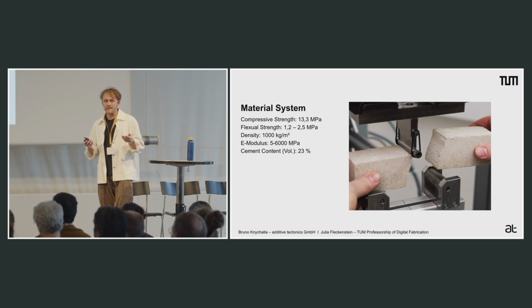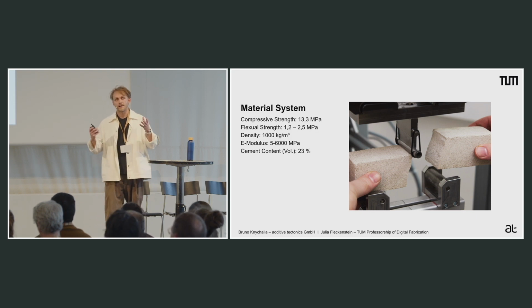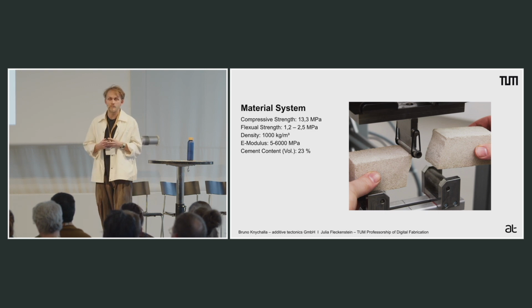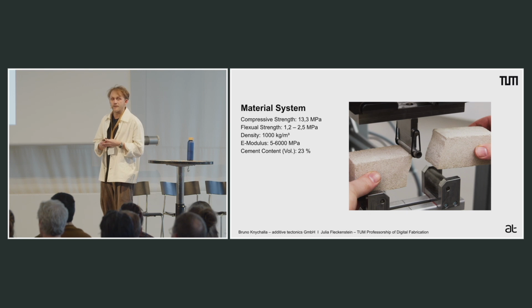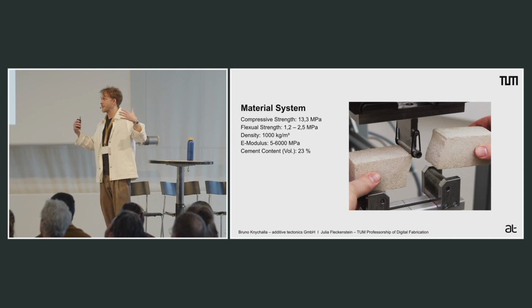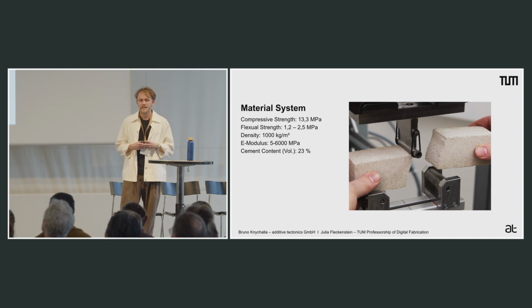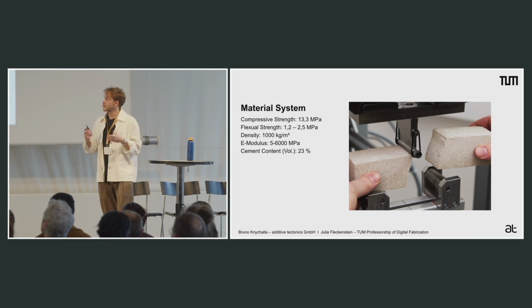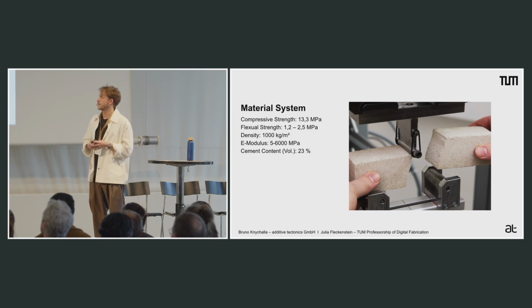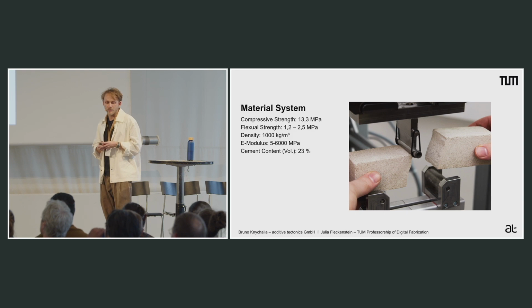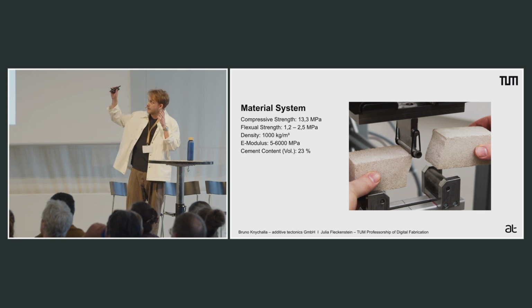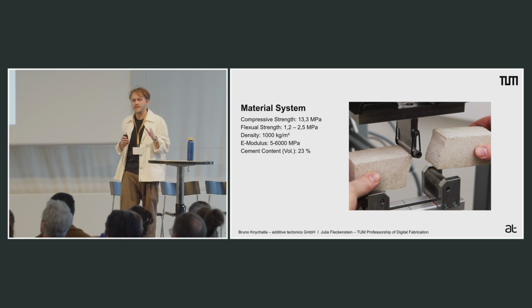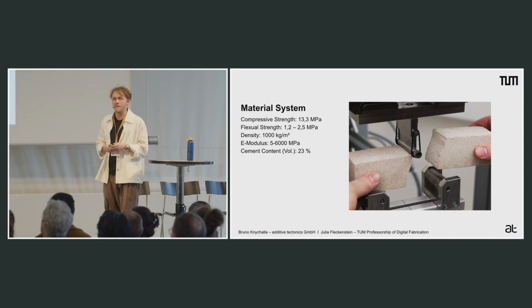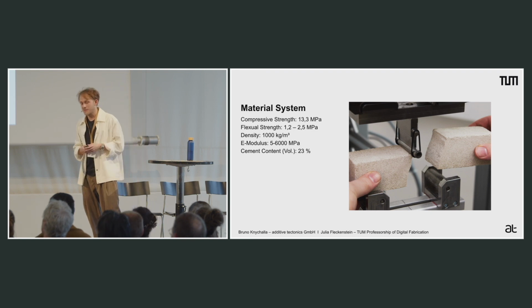We developed a completely new material for this because we knew we wanted to have a functioning prototype. It's based on ordinary Portland cement, and we needed to print a very big part for the first time. The material that we developed had a density of 1,000 kilograms per cubic meter, and the rest of the material properties point in the direction of infra-lightweight concrete, which meant that probably the insulation properties were very good.